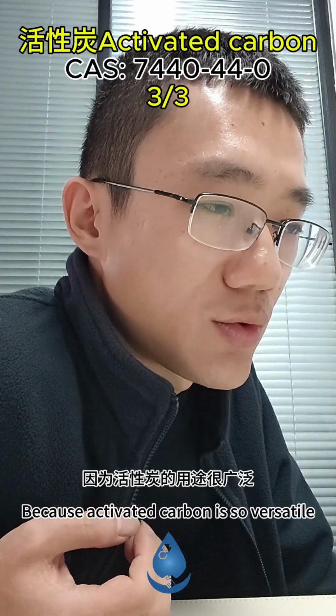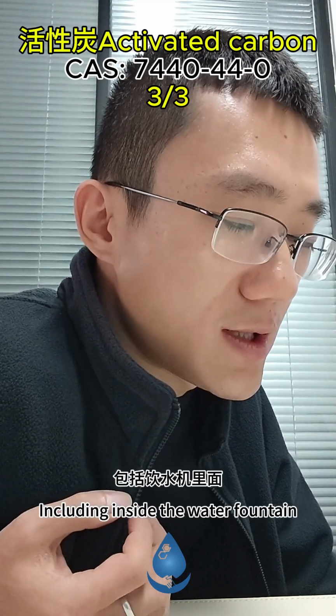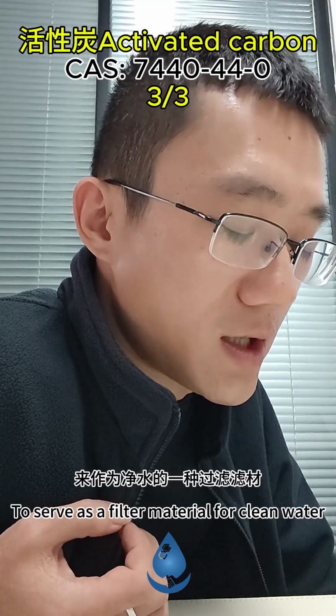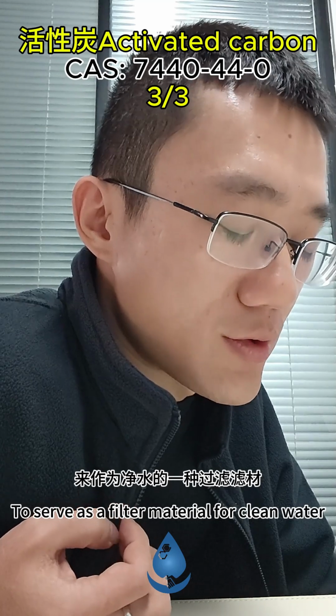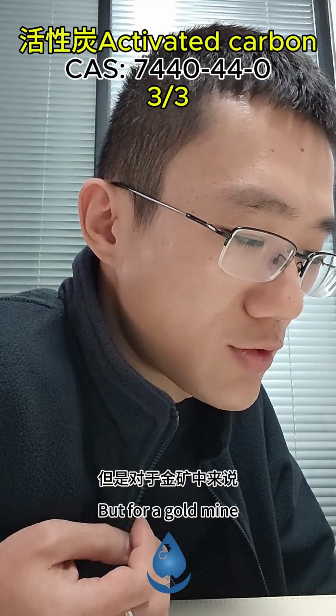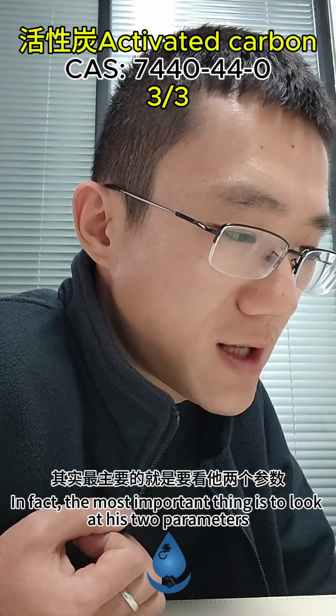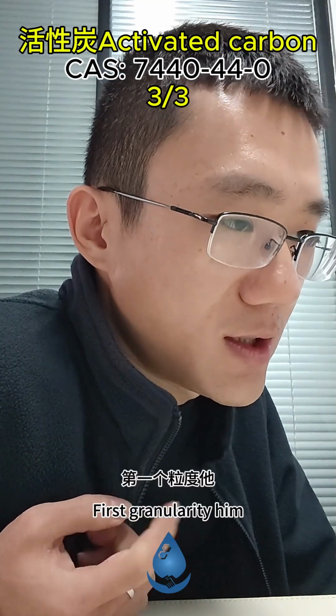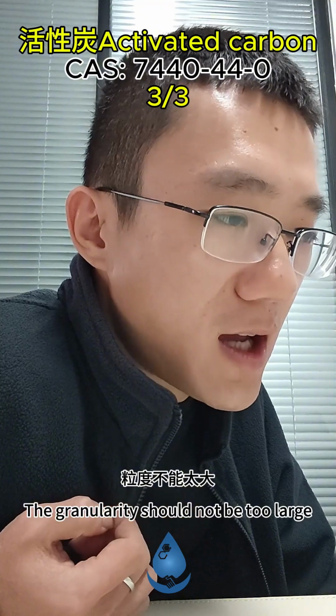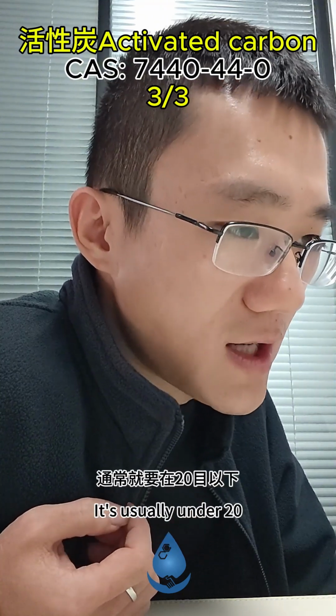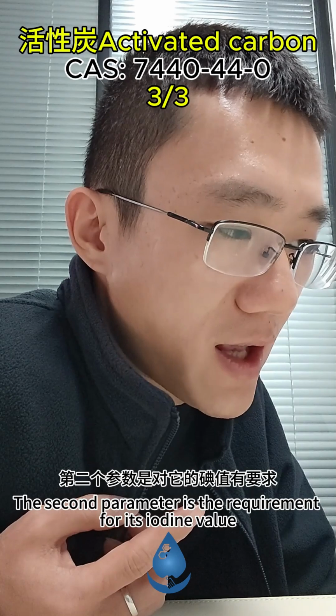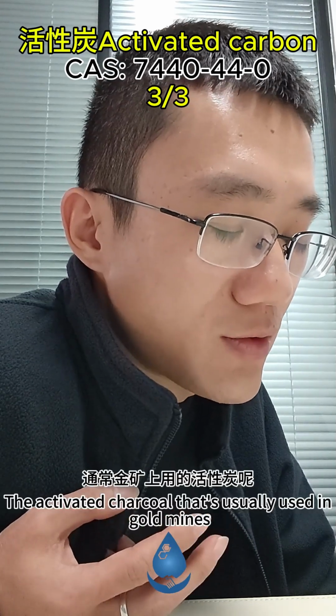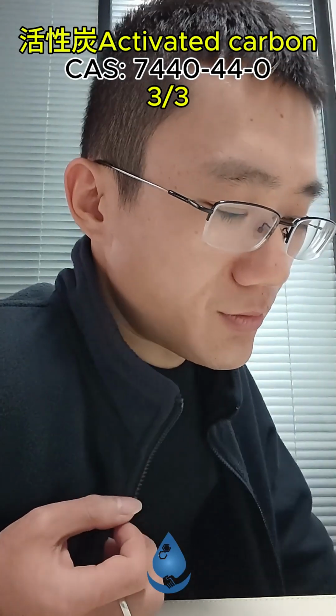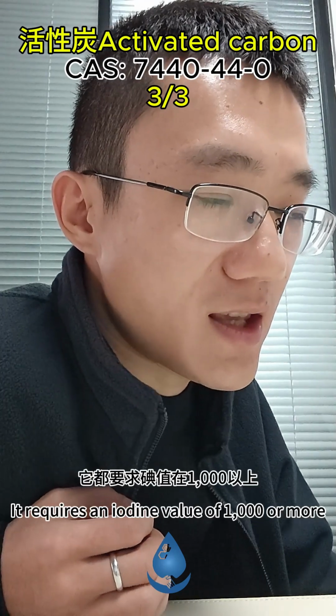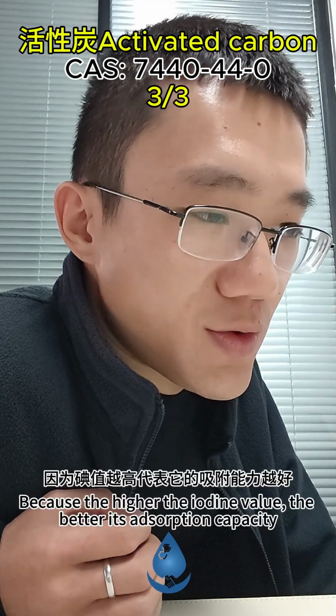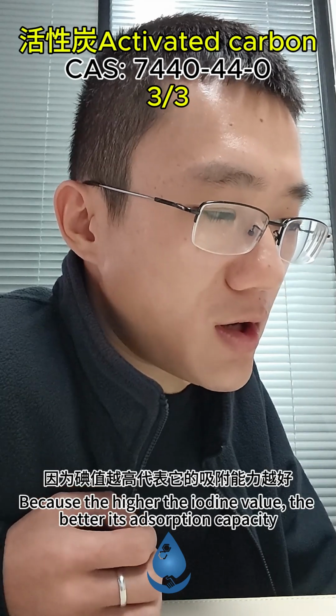Because activated carbon is so versatile, including in water fountains, it can be used as a filter material for clean water. But for a gold mine, the most important thing is to look at the parameters. First, granularity. The granularity should not be too large, usually under 20. The second parameter is the requirement for its iodine value. The activated charcoal usually used in gold mines requires an iodine value of 1000 or more, because the higher the iodine value, the better its adsorption capacity.